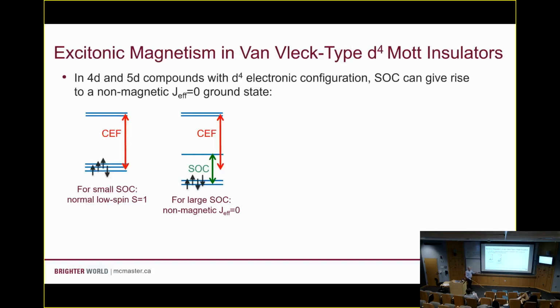Should be magnetic. When the spin-orbit coupling becomes stronger, that breaks the degeneracy of these t2g levels. And now when we fill up our levels with our first 4 electrons, the J effective 3/2 levels here are totally filled. These are totally empty. So we have something that's effectively non-magnetic. This is J effective equal to 0. So you're saying, why are we studying magnetic materials that have no magnetism?